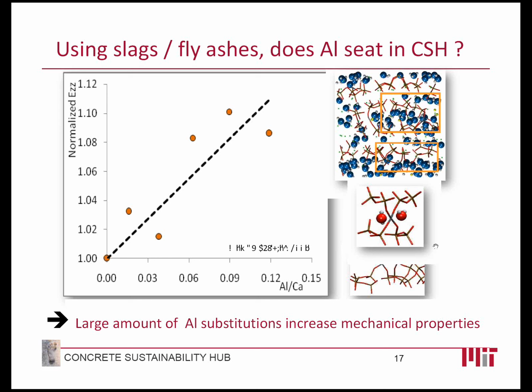Is the fly ash slag added to the raw materials in clinker manufacture to gain the required substitution? I don't know the natural amount of aluminum in the cement structure. I don't have the numbers with me, but the idea is maybe to go beyond that point, beyond a few percent, and maybe we can go to like 20, 25%, 30%. That will also require some nano indentation on those controlled samples, for instance.